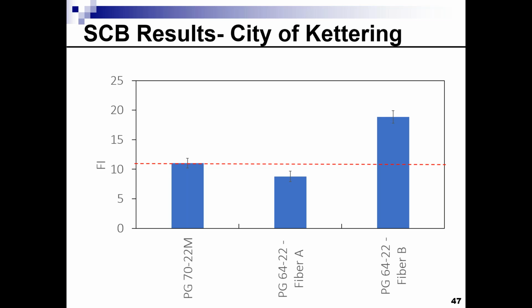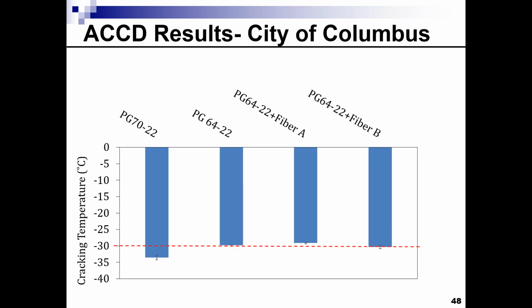In terms of the city of Kettering, it seems that with fiber B, the flexibility index was higher as compared to the PG70-22 polymer modified, while the fiber A mix with a 64-22, as you can see, had a slightly lower, but still, I would say it's statistically similar to that of a polymer modified.